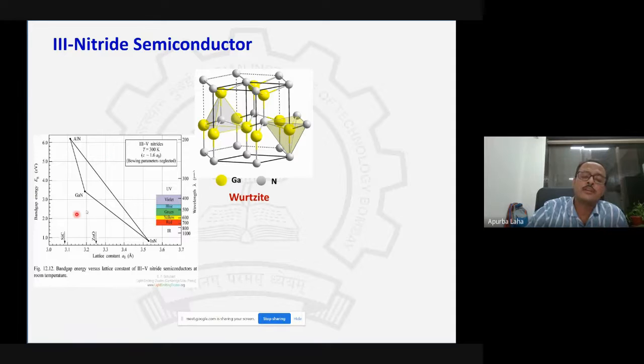In between comes gallium nitride, which is 365 nanometer considering the band gap, and then indium nitride, which gives you light somewhere in the 1.5 micron or IR range, given the band gap is 0.6 or 0.7 electron volt. No other material system can give you such a wide spectrum. That is why gallium nitrides or III-Nitrides are so interesting. And not only are they interesting in terms of optical or optoelectronic properties, they also have wonderful electronic properties. For example, in mobile communication, base station communication, and high power transistors, the basic devices are made with gallium nitride based heterostructures.